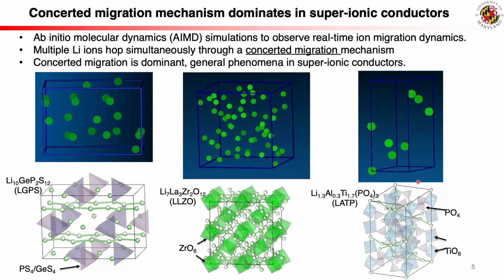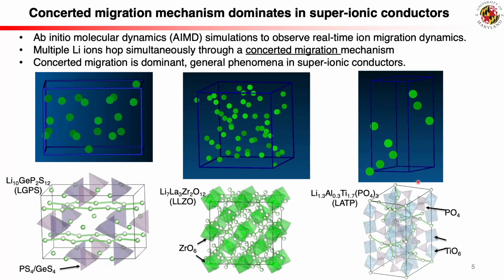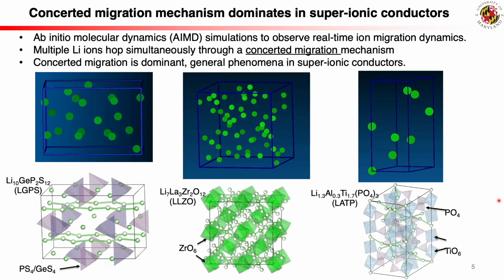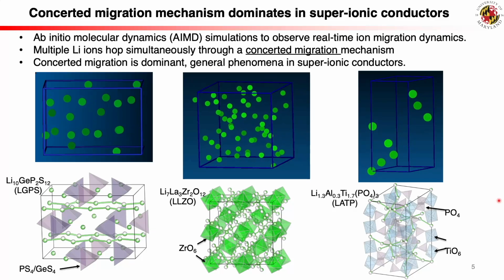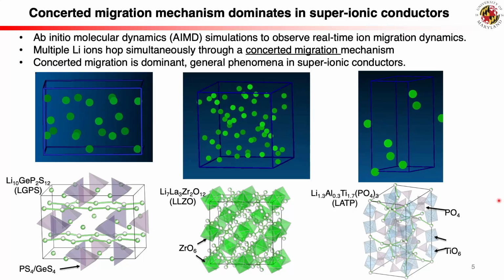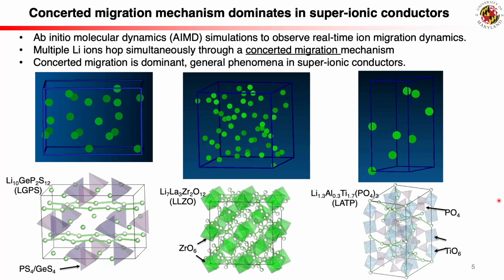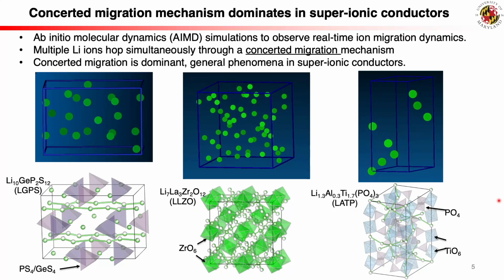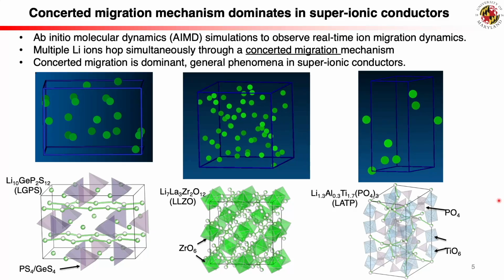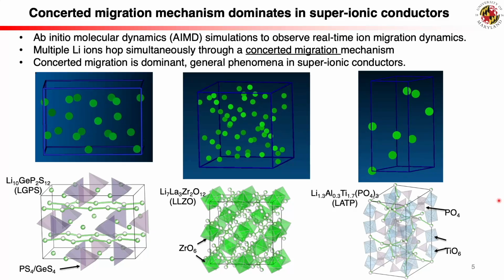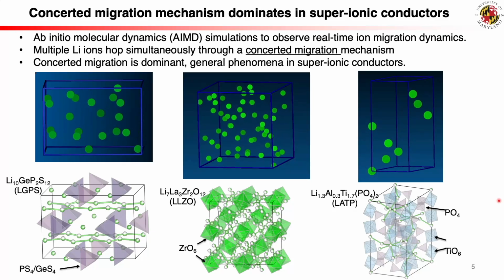Why look at materials with different structures? Because they wanted to see if this concerted migration was universal, not just a fluke of one particular structure. So what did the simulation show? There was strong evidence. First, they saw a strong time correlation in the lithium-ion hopping. When one lithium ion hopped, its neighbors were very likely to hop around the same time, more like a coordinated dance.